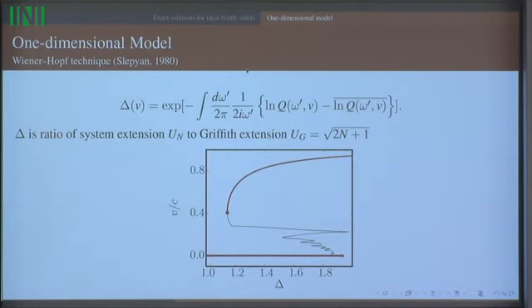So here's what the solutions look like. There's first of all a static branch. So if you grab the system and you start dragging the edges up very slowly without giving anything any velocity, then you actually go way past this point 1 where there's enough energy, up to nearly 2, before the system figures out that it can move, because it's trapped in a metastable minimum. This phenomenon, this existence of a static branch, is called lattice trapping, and that was found by Rob Thomson in 1969.